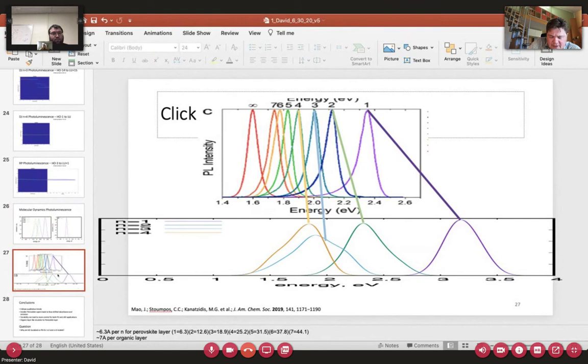If the cell size is not optimal, it could be that the geometry escapes the configuration with the strain, and then the gap expands or shrinks. No, here it looks like it shrinks along the molecular dynamics trajectory. Yeah. That was the only thing I could come up with for why that is, but I need to put some more research into why that's occurring.